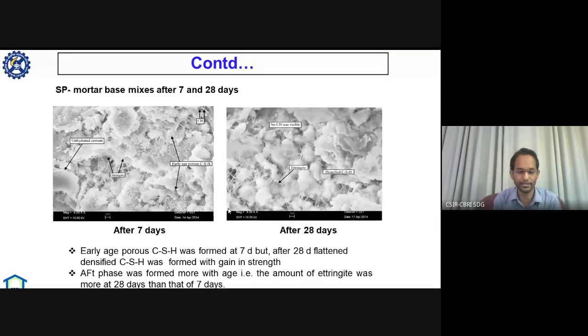Therefore, the strength was very high, and AFT phase was more in case of 100% replacement level of stone slurry. Generally, what happens when C3A, which is the alumina phase of the cementitious system, reacts with gypsum, it forms ettringite, which is denoted as AFT. And if the gypsum is depleted, if enough amount of gypsum is not there, then that C3A converts into AFM phase. But when we add calcium carbonate, the calcium carbonate reacts with AFM and generates AFT again.